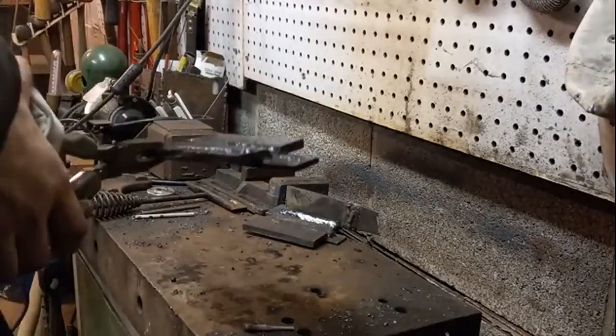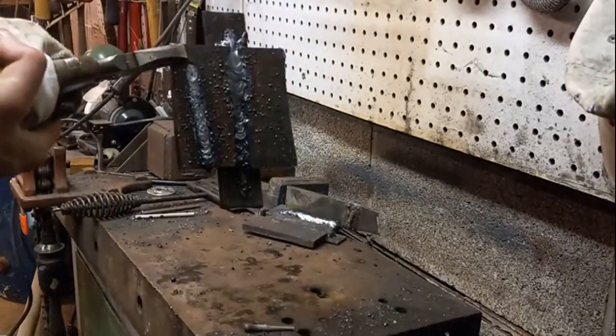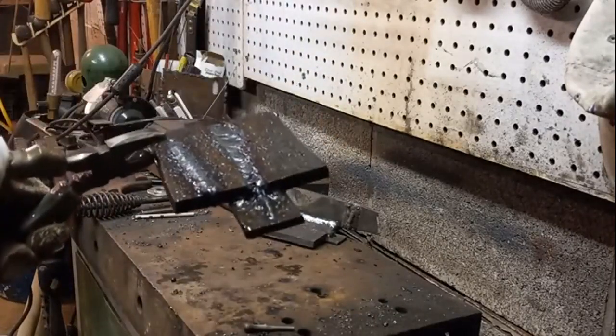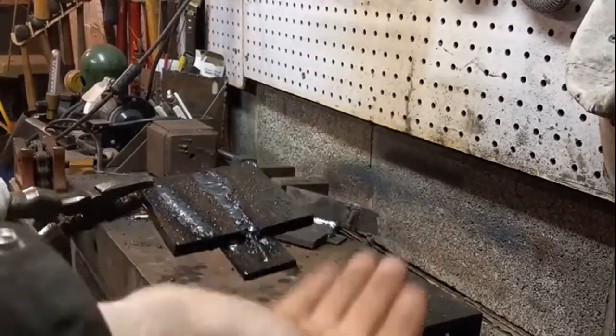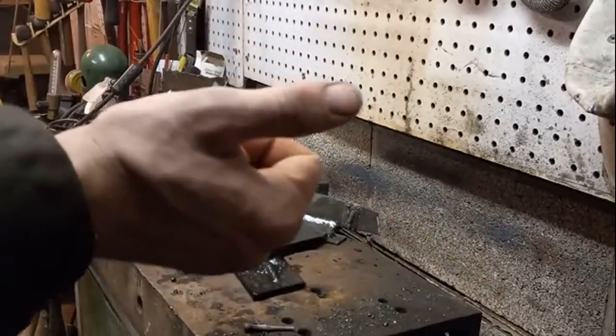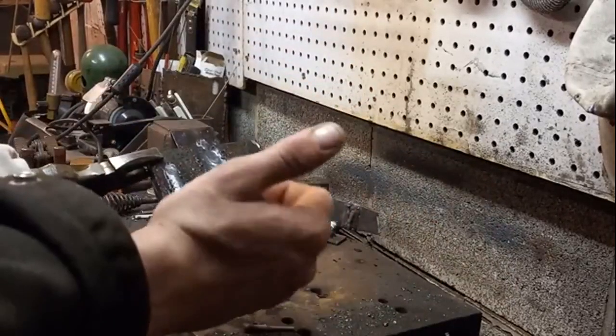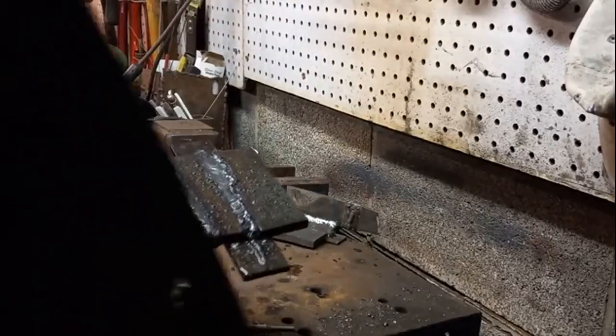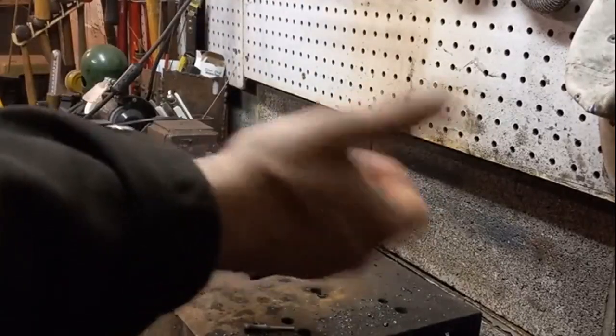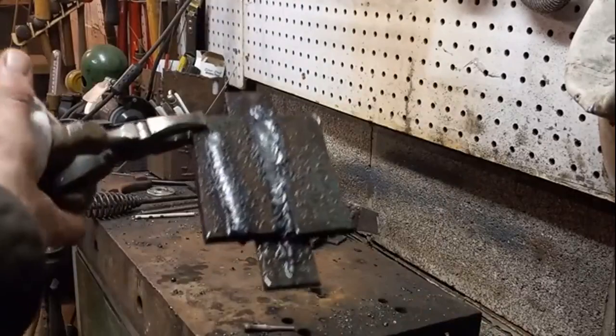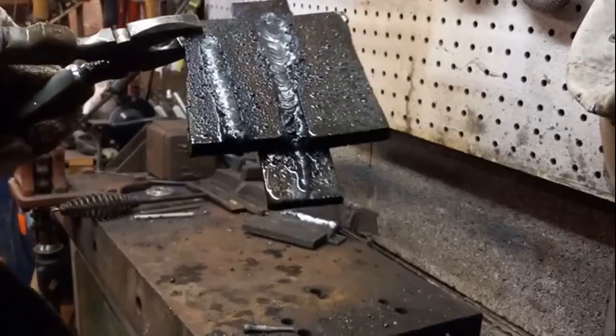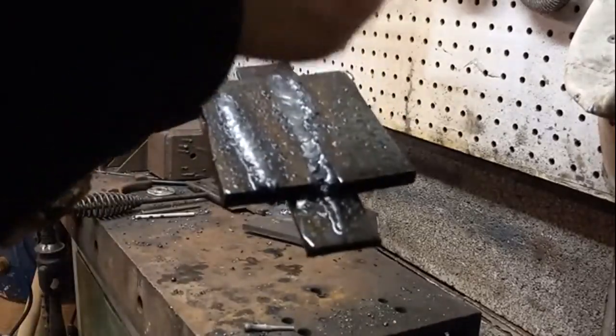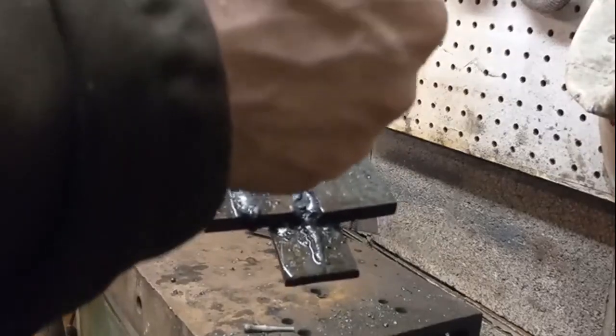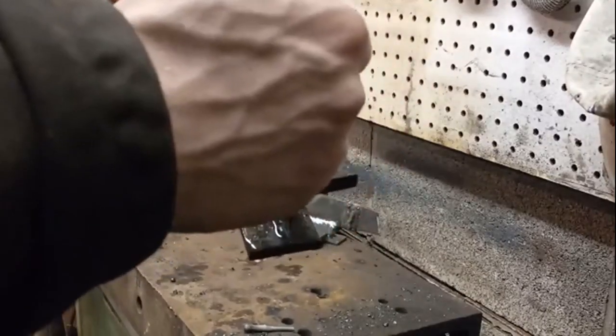End result of the 1G, I'm less than impressed. So I started doing that little side-to-side weave. In reality, I should have done a multi-pass stringer bead, but I started trying to do a little weave back up through there, and it could have been because of the large rod diameter and the small space of that V groove, the molten slag of the rod in its own puddle was almost smothering it out.